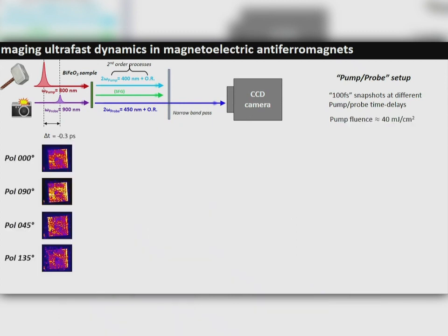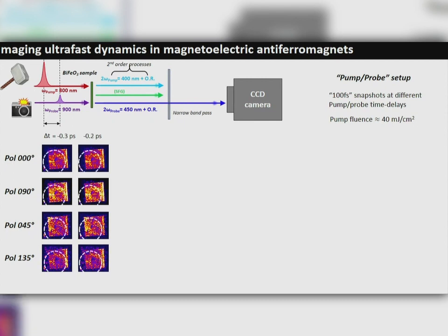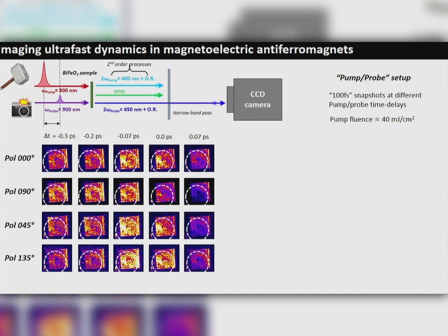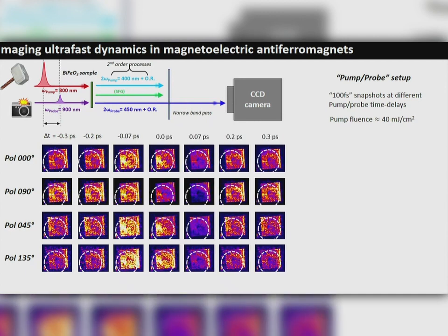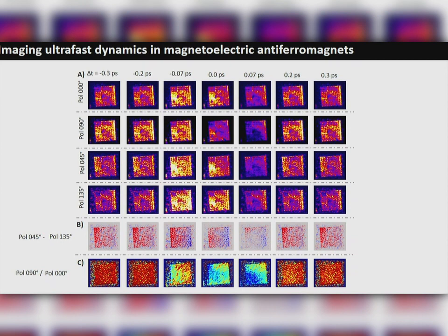So what we are doing is taking snapshots at some delay. The pump was focused here on about 10 microns. I forgot to say it's a 10 micron square. And then we do that as we sweep the delay line, and like this we are able to get a snapshot of the time evolution of the second harmonic signal. As we do this, we can get different images. At negative time, when there is no excitation, the red and blue show different kinds of antiferromagnetic domains. You can see that this is evolving with time, and around T0 we can see a large evolution, and this is what we are trying to investigate.